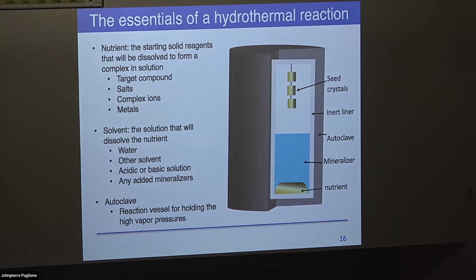And then for much more sophisticated syntheses, for example, the ones I showed you with the quartz crystals coming out of that large vessel, you'll have seed crystals, which might be in a different region of your autoclave. These seed crystals are basically just to help seed your crystal growth, and you grow larger crystals from that seed crystal. Most of the time, when you're doing something with a seed crystal, you need a temperature gradient. You would have dissolution in this regime and growth in this regime, and you would tune your pressure or your temperature in those different regimes so that the two different things are met.